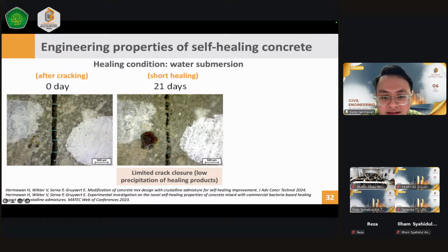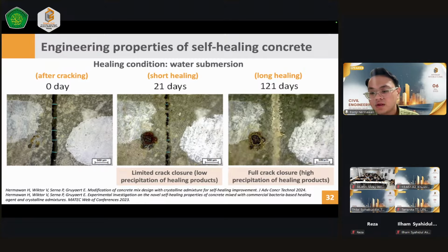So in the middle, there were some minerals formed inside the cracks and also at the crack mouth, on the crack location. And if we allow a longer healing time, what's going on? There will be a full crack closure with a very dense precipitation of the healing product. So this type of healing agent can promote the autonomous healing mechanism.